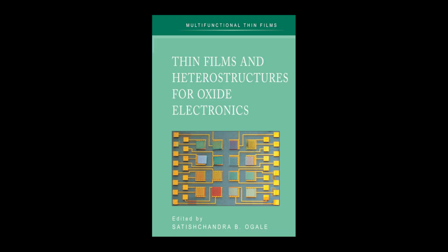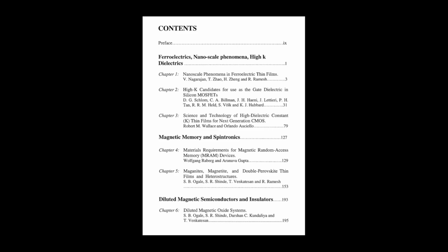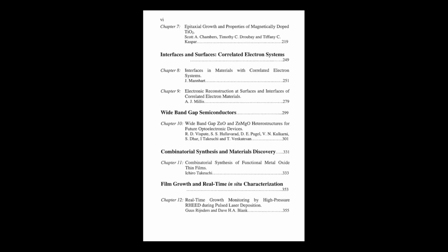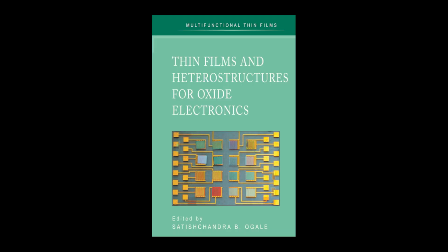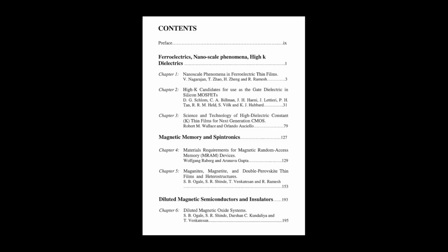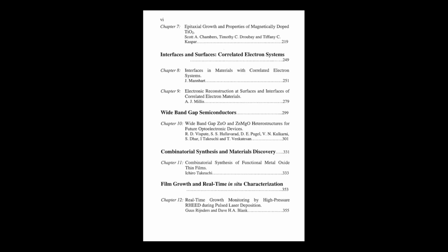That's barely measurable. Why so low if it's supposed to be 100% spin polarized? Again, it comes down to interface quality. Suspicions fell on things like maybe the interface wasn't pure Fe3O4, maybe a dead layer formed, or perhaps competing iron oxide phases, like Fe2O3, which is antiferromagnetic, formed right at the boundary, killing the spin polarization just where it mattered for tunneling. So whether it's conventional metals or exotic oxides, the story for high-performance MRAM seems to be: control that interface down to the last atom or you lose the spin signal.